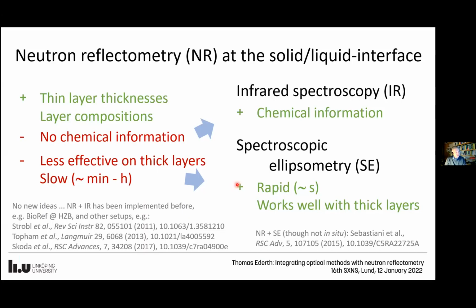Yes, so I'm sure that a number of people in the audience can testify to the benefits and advantages of neutron reflectometry, not just at the solid-liquid interface, which is what we will be dealing with, but despite all the greatness of reflectometry, there are some disadvantages. Among these, there is no chemical information in these measurements, it doesn't work well with thick layers, and it is relatively slow.